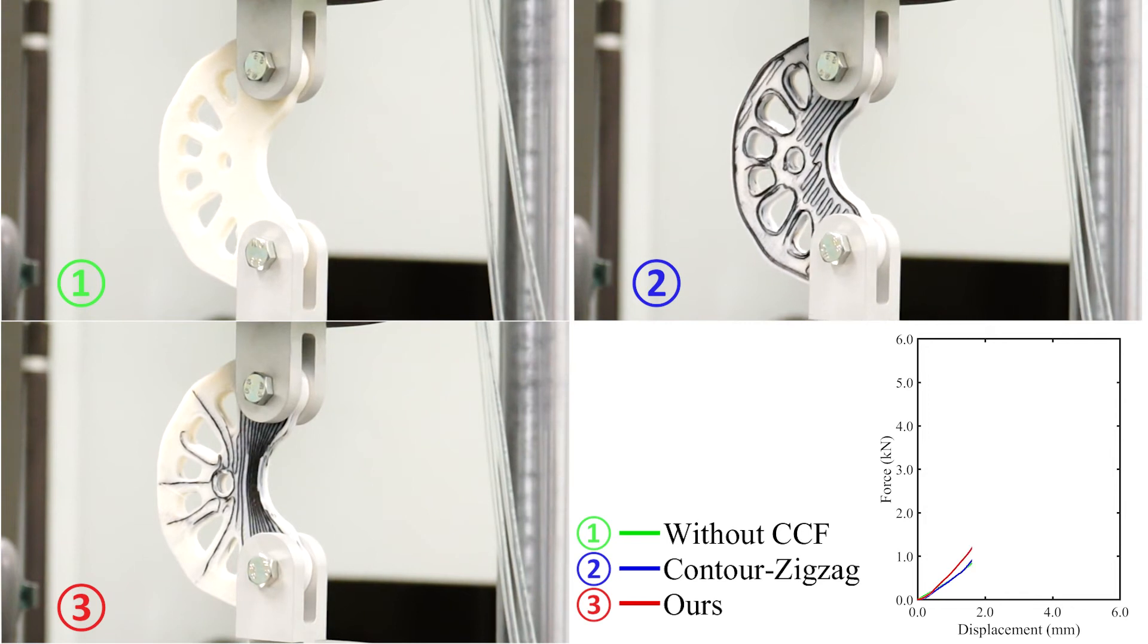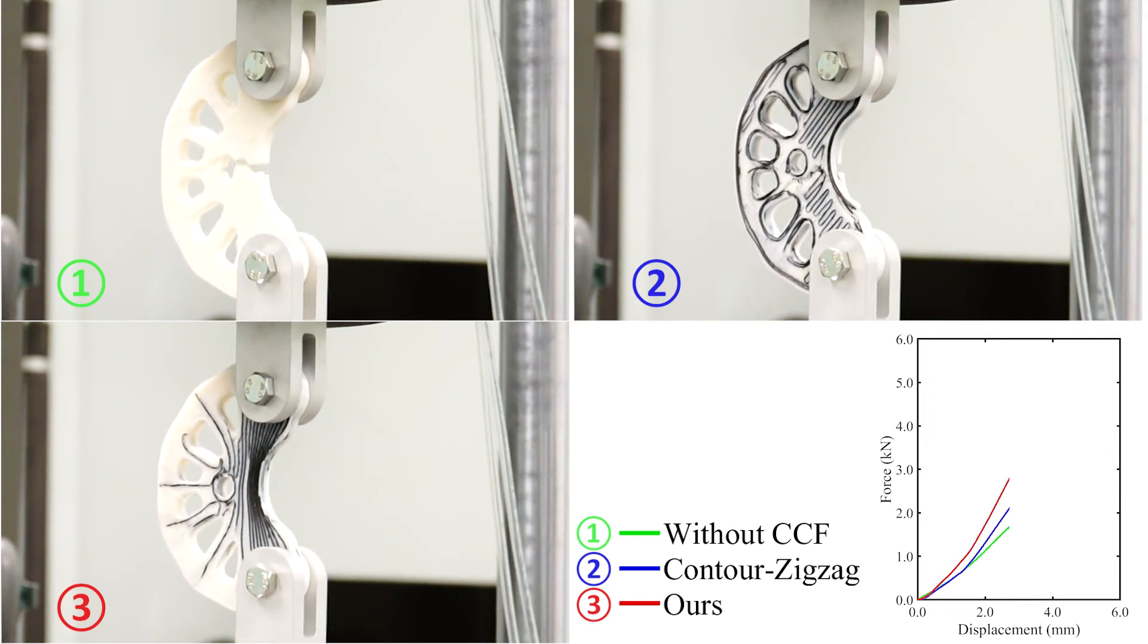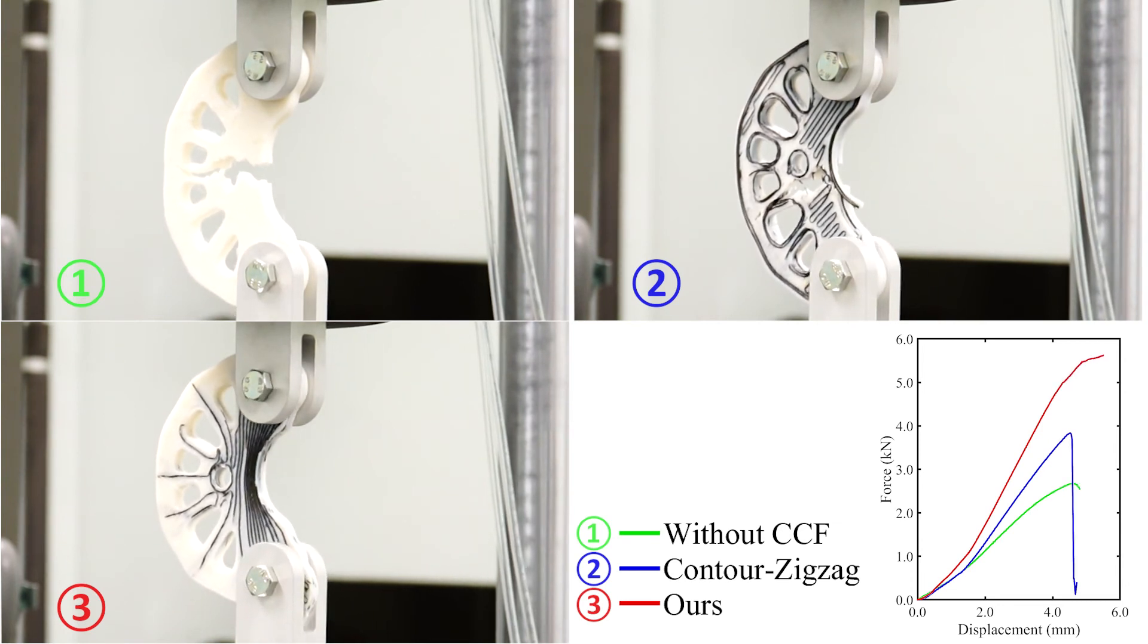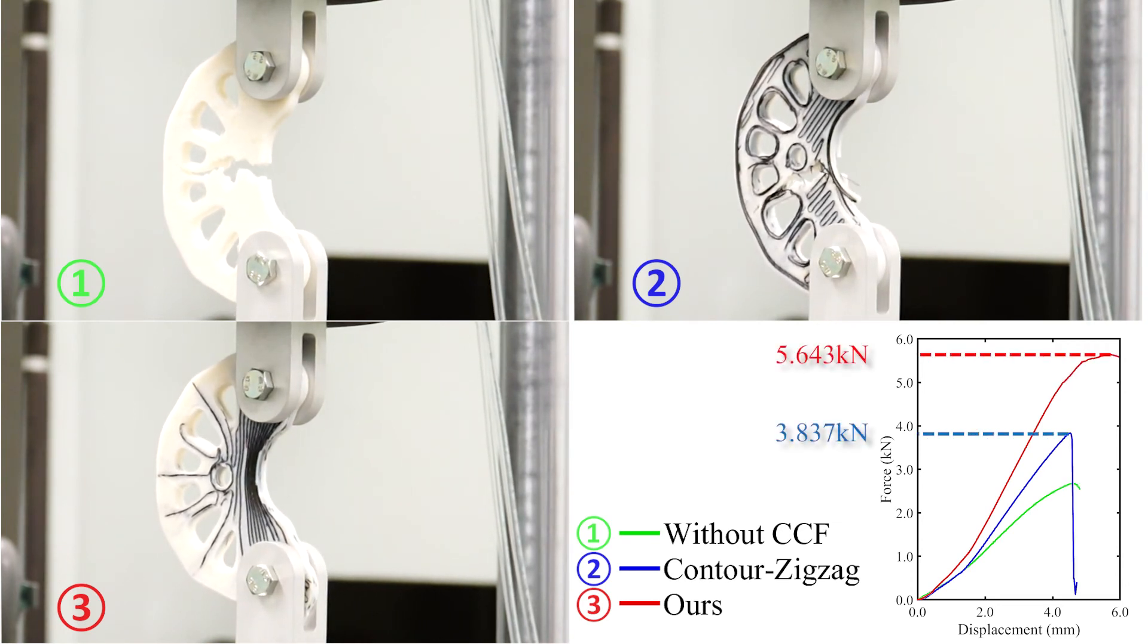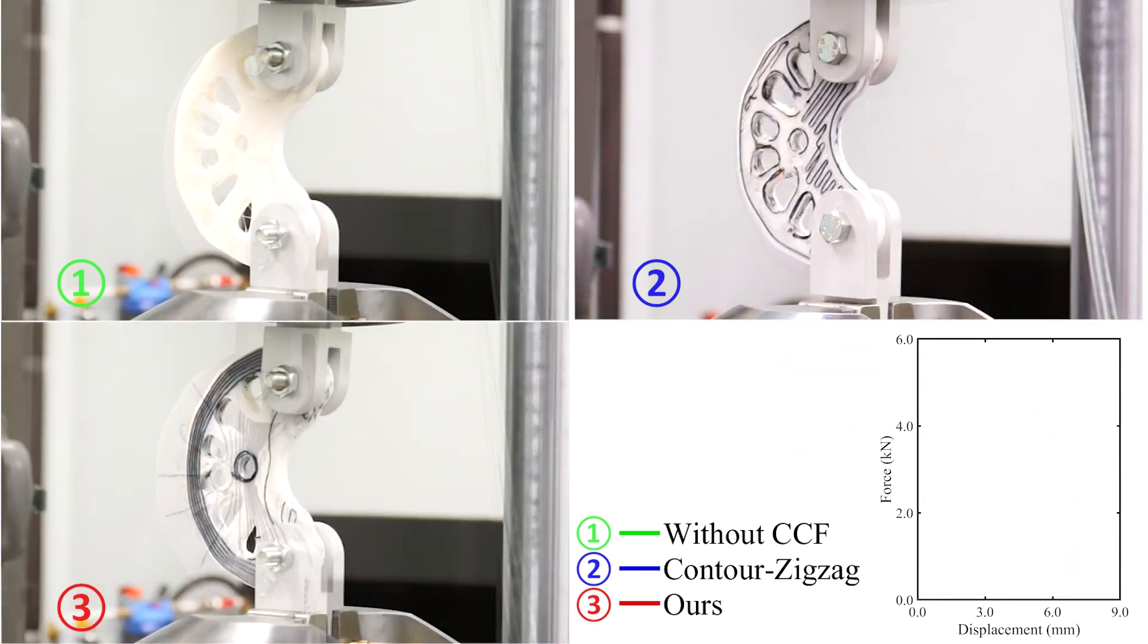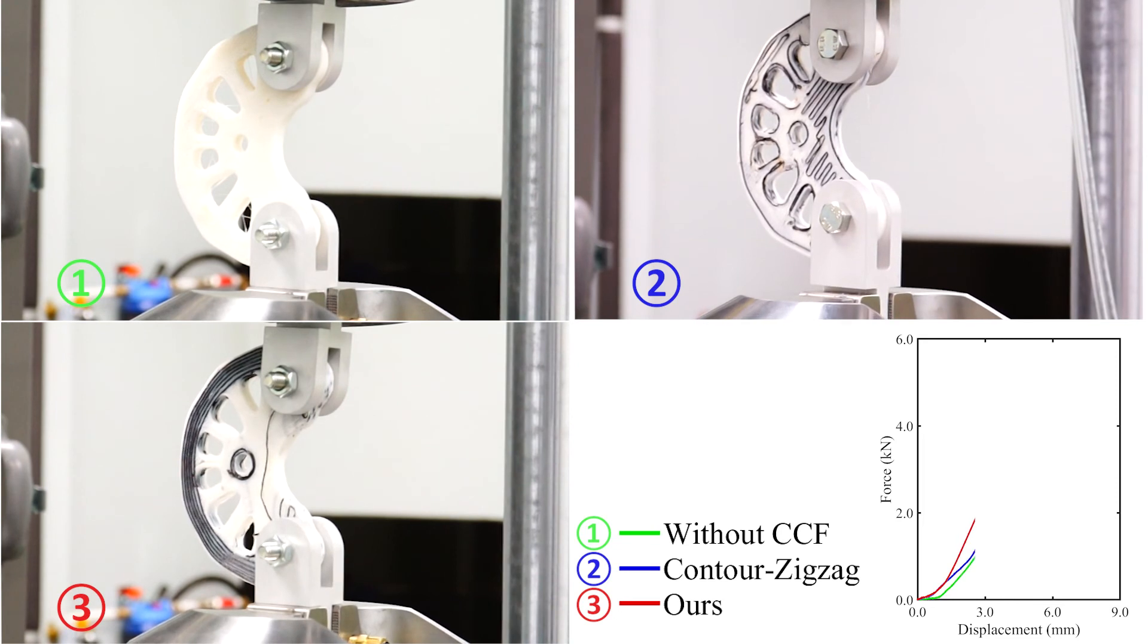Here, we show the results of the shear model under both tensile and compression loads. The breaking force of our method is increased by 47% in tensile test and increased by 18% in compression test.